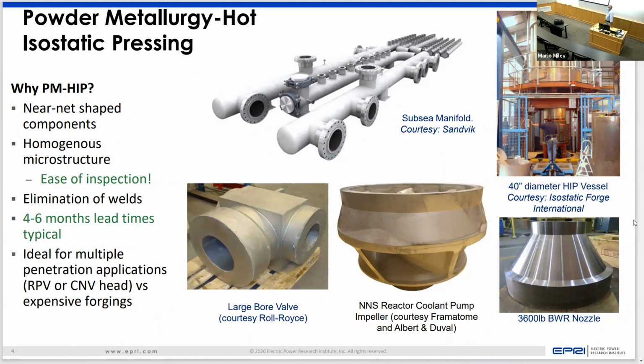So what is the purpose in using powder metallurgy and hot isostatic pressing? Powder metallurgy means you start with a powder, you basically put it into a canister or a can that's very close to the shape of the component you're trying to build or produce. You put it under extreme pressures, around 15,000 PSI and around 2,000 degrees F, and it consolidates that powder. That powder creeps on itself and basically consolidates into a solid monolithic structure.